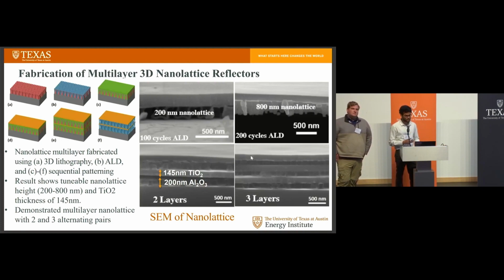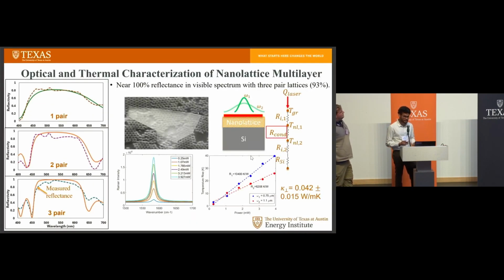consisting of different lattice heights from 200 nanometers to 800 nanometers, with which we can vary the wavelength at which the peak reflectance is observed. We have also successfully fabricated 2-stack and 3-stack lattices, as seen from the SEM images over there. Coming to the optical characterization, we used a Cary 5000 spectrophotometer in order to characterize the reflectivity versus wavelength for the visible spectrum for now, from 400 to 700 nanometers, as you can see from this image. And compared to the 1 pair, the 3 pair lattices have way higher reflectance for a really broad band, which is because of the refractive index mismatch that is generated by the multiple layers which are present.